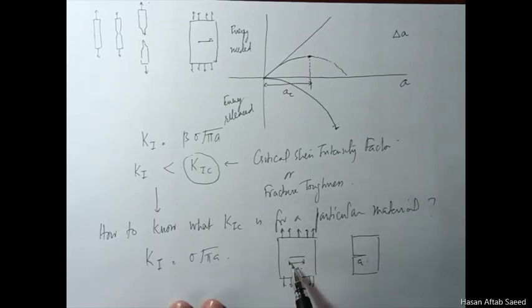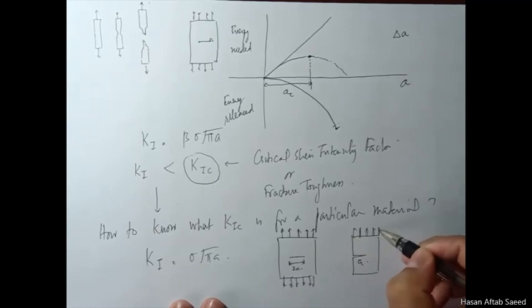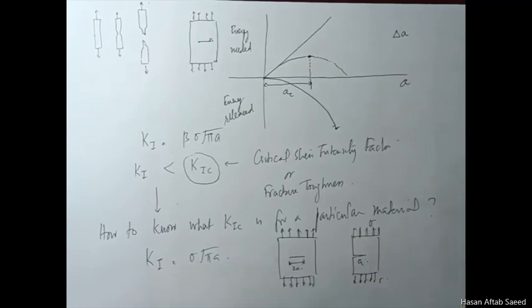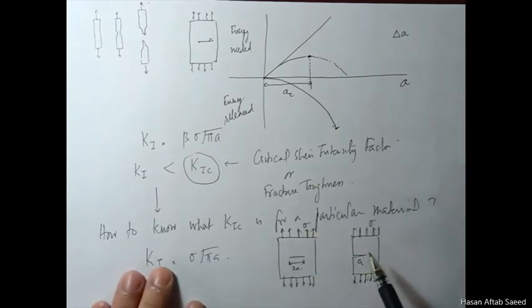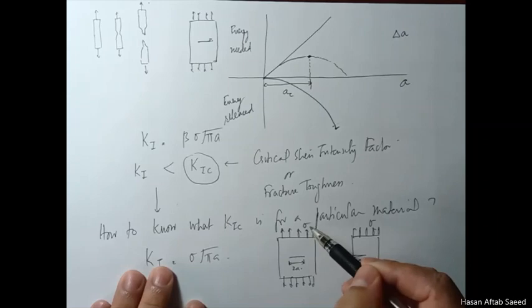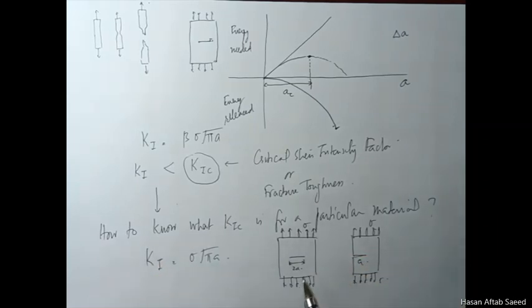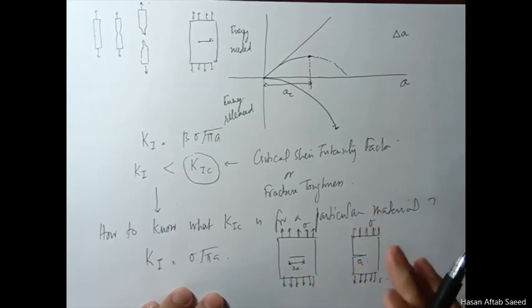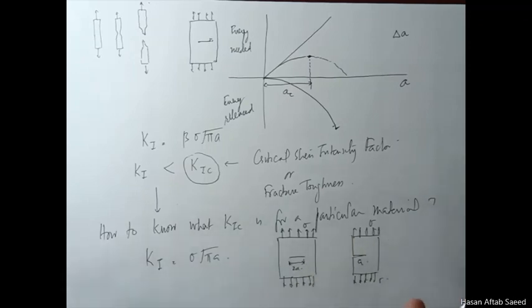For example, take an edge crack and a center crack under the same load sigma. The center crack will be 2a length, the edge crack will be a length. They are equivalent, but obviously this is slightly benign. The stresses here will be slightly less, and I'll leave the students to think of the reason why. The stresses here will be similar, but this will have slightly more stresses, and this has more ability to run away. In other words, the beta for this will be higher than the beta for this one.